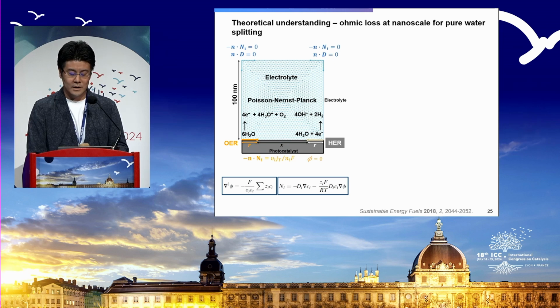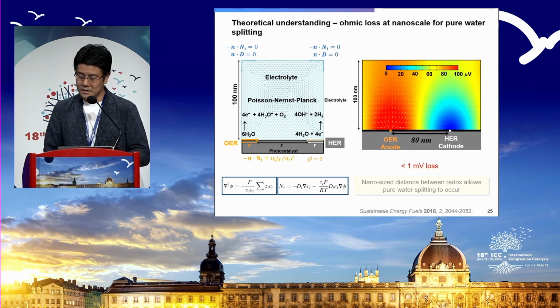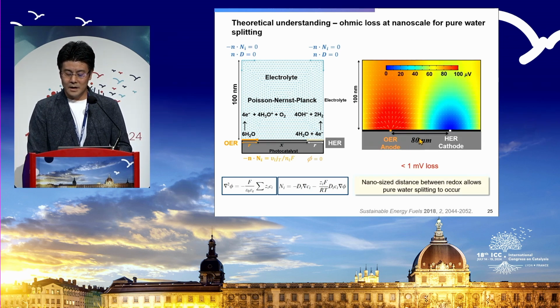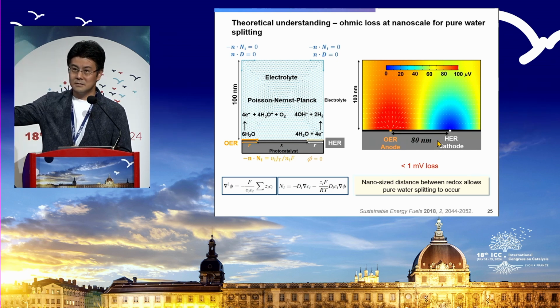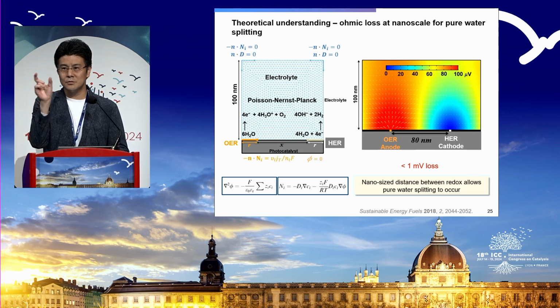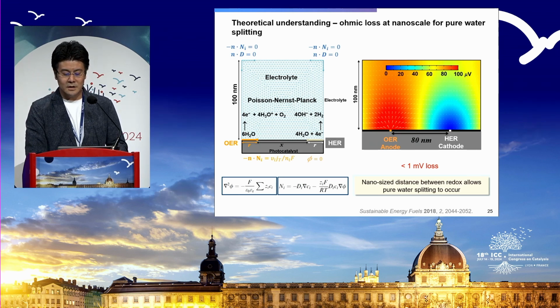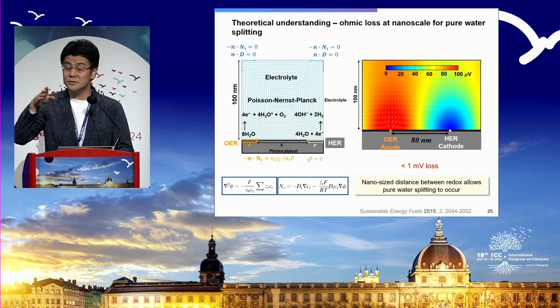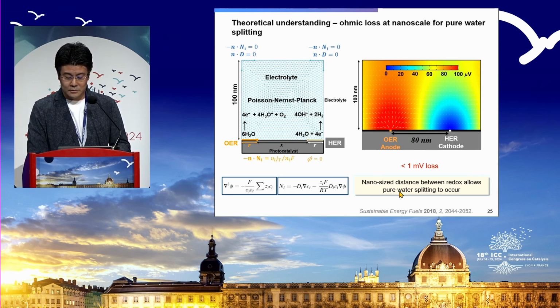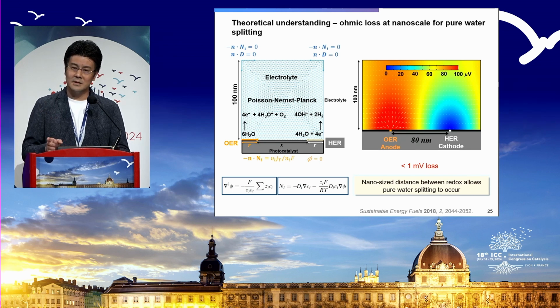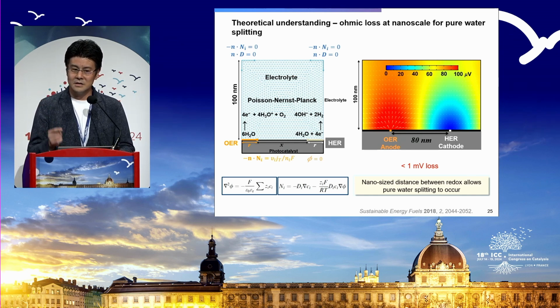And first, we have to solve the Poisson-Nernst-Planck equations, as shown in these equations. Then we try to simulate even far away, over 80 nanometers. So Rengui was talking about this facet difference, right? But it should be much shorter than 80 nanometers, so I'm exaggerating. Even if you had 80 nanometers between hydrogen evolution and oxygen evolution, this is still less than 1 millivolt of loss. So solution resistance is something that you can definitely minimize in the case of overall water splitting using powder semiconductors. This is one of the most beneficial points of overall water splitting, generating hydrogen and oxygen together from the same surface.